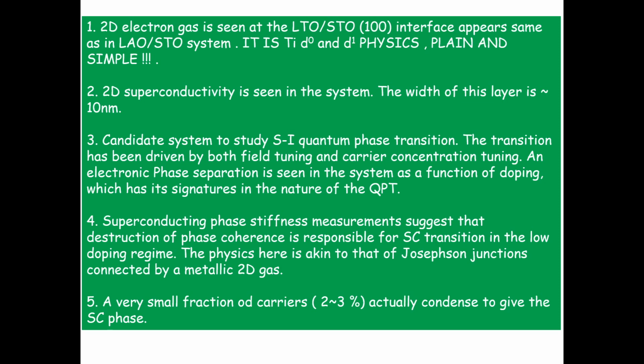When you transfer electrons from the top, some of them are in strontium titanate, all of them are in d0. Once you transfer more electrons, some of them go in d1. So you have d0, d1, and that is giving you the conducting layer, and that's where all the action is. And the width of the superconducting layer is about 10 nanometers.